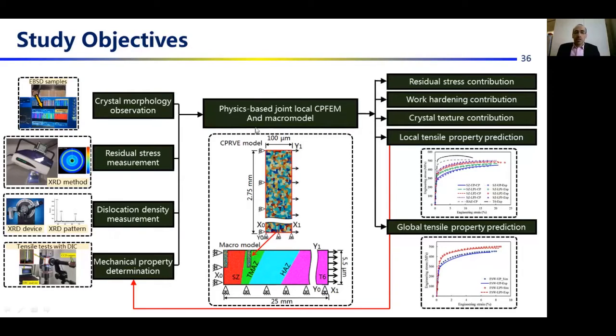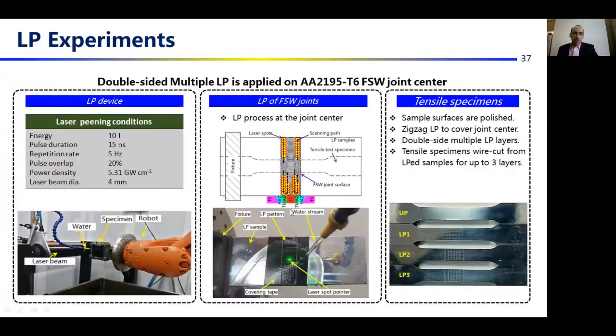In this study, joint local physics-based CPFEM models are developed by including the microstructure attributes such as crystal morphology, residual stresses, and dislocation density. This model will quantify the strengthening contributions of laser peening-induced residual stresses, work hardening, and crystal texture variations to predict the improvement in joint local and global tensile properties after laser peening.